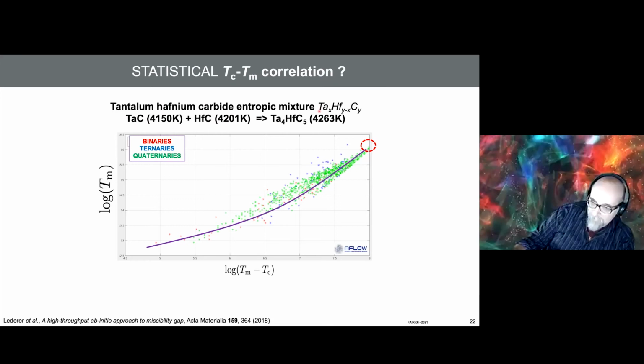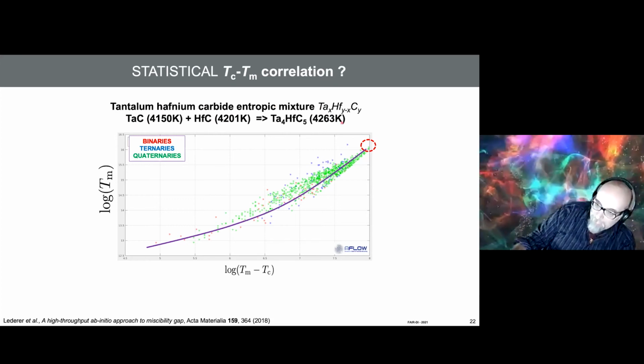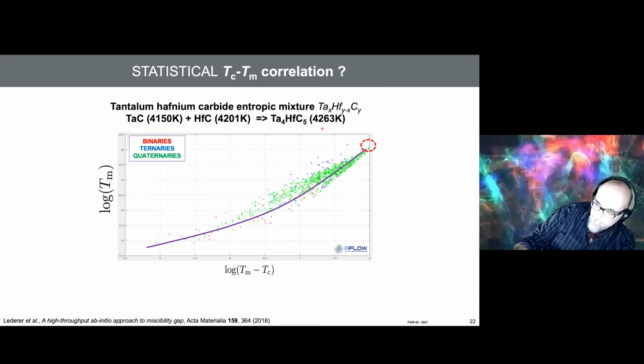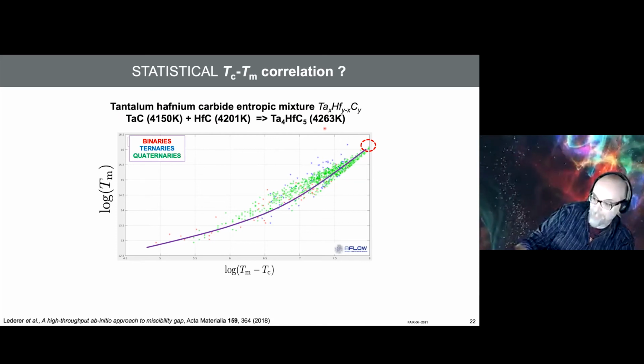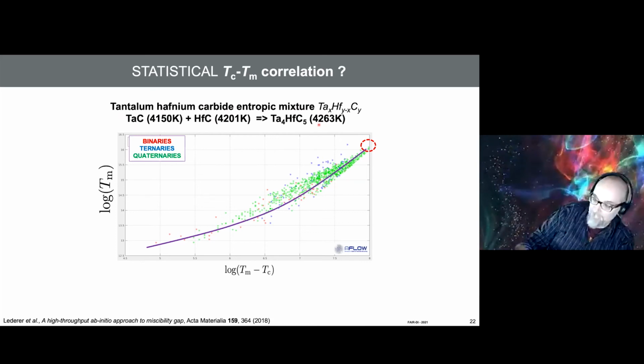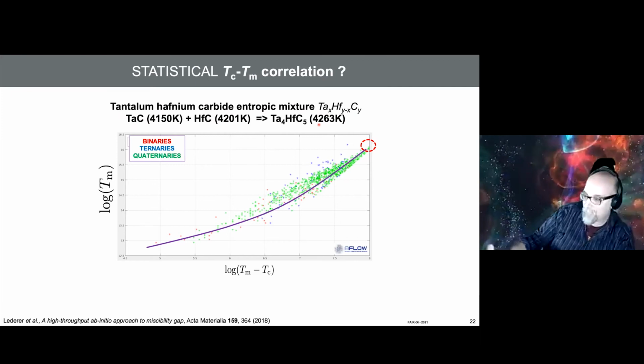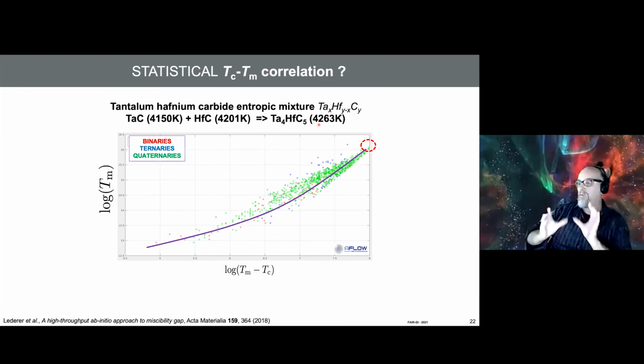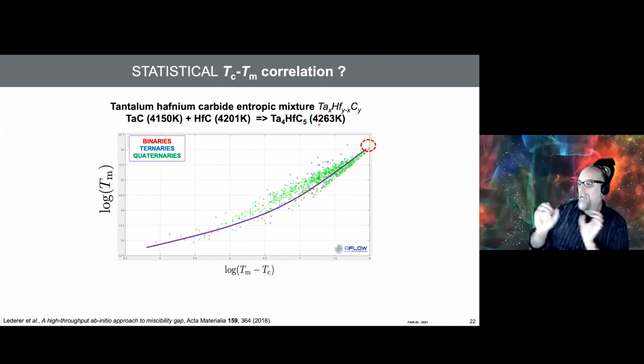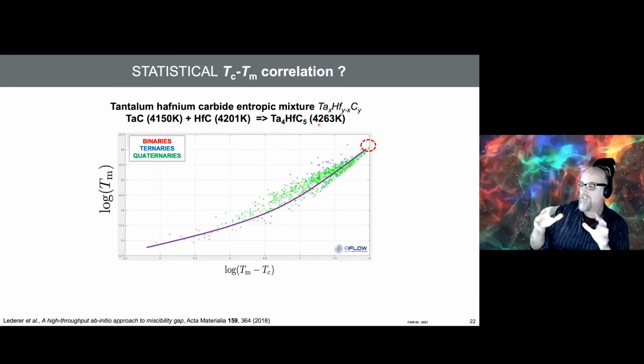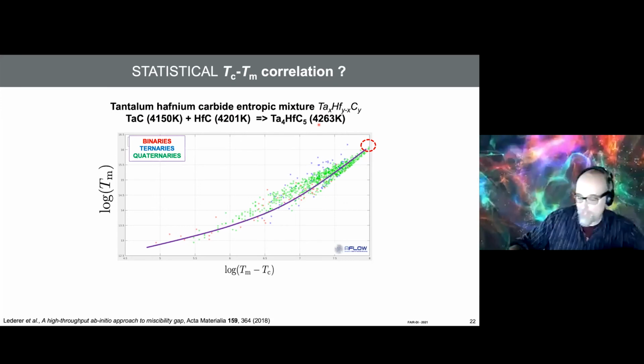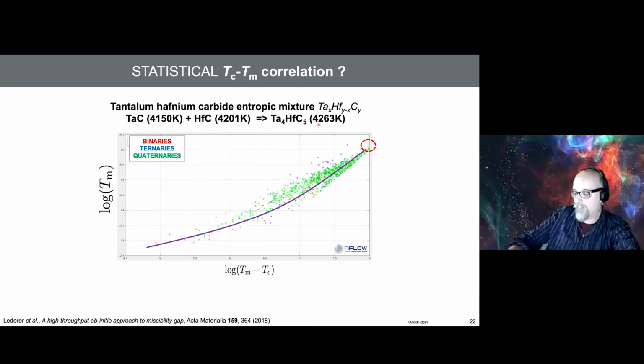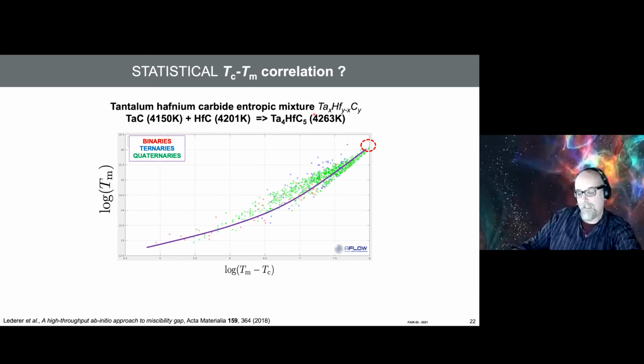And audience, making the experiments to really measure these things is highly non-trivial, because you cannot put this in a crucible. It melts. So you need to have this material suspended in argon, and then shoot a laser and look for a reflection. You see if you have a melting or not. This is highly non-trivial.